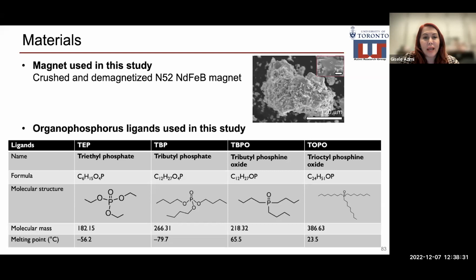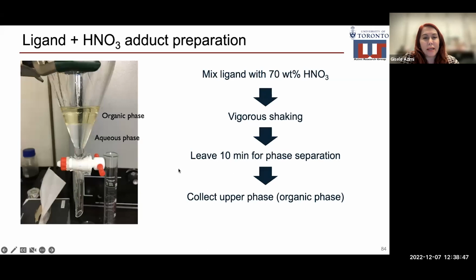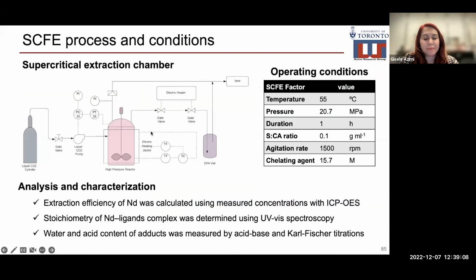And here we use 4 organophosphorus ligands: triethyl phosphate or TEP, tributyl phosphate, TBP, which we were using in the previous project, tributyl phosphine oxide, TBPO, and trioctyl phosphine oxide, TOPO. To make the ligand an HNO3 adduct, we mix the 4 ligands that I mentioned previously, separately with 70 wt% nitric acid. We vigorously shake it and leave it for 10 minutes to do the phase separation. The 2 phases, organic and aqueous, separate, and we collect the upper phase as the organic phase.